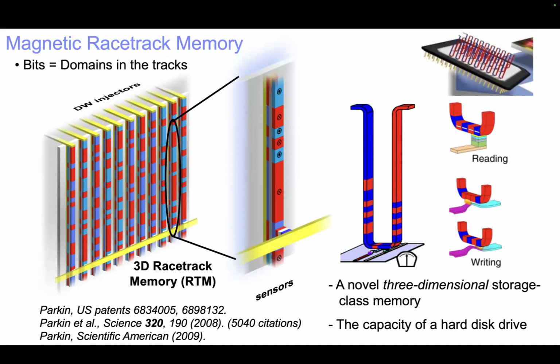And then the concept is you pass current into this racetrack, and the idea is that all the domain walls would or should move in the same direction. Therefore, as you can see in the surface of a silicon wafer, where we would use conventional CMOS circuits to generate the needed current pulses to move the domain walls and to detect them, you could store, let's say, in 1 nanowire, 100 domain walls in the third dimension, therefore increasing the storage capacity over a conventional charge-based memory device with a single memory element per device by 100 times, by the number of domain walls in this racetrack.